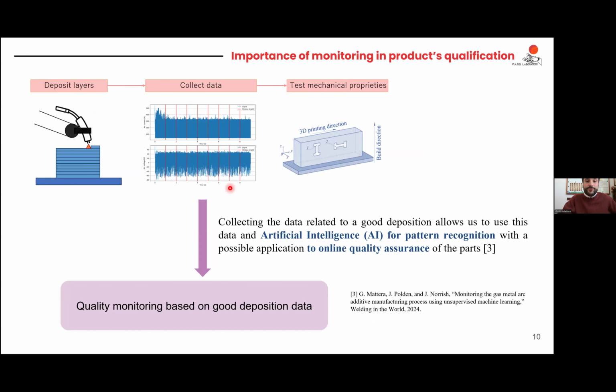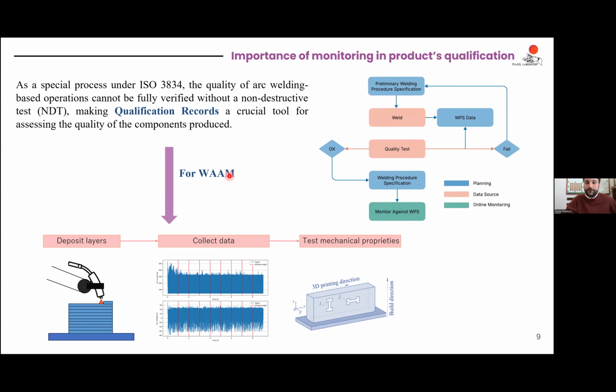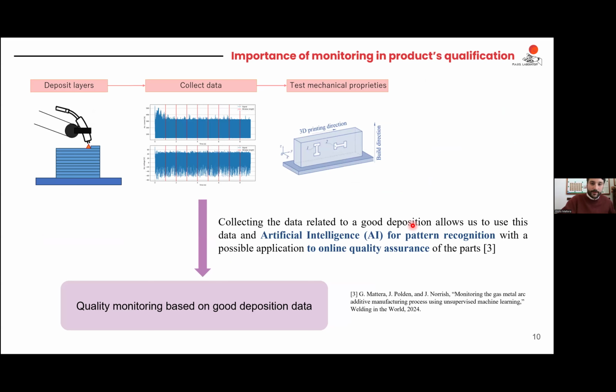So this means that process monitoring is always something that happens with respect to the qualification procedure, because once you have a quality part, you put this quality part in the procedure specification, and then you always have to monitor your process with respect to the qualification procedure. So you have to be sure that what you are depositing, what you are building up as an additive manufacturing part, is building up in the same way that you observed during the qualification procedure.